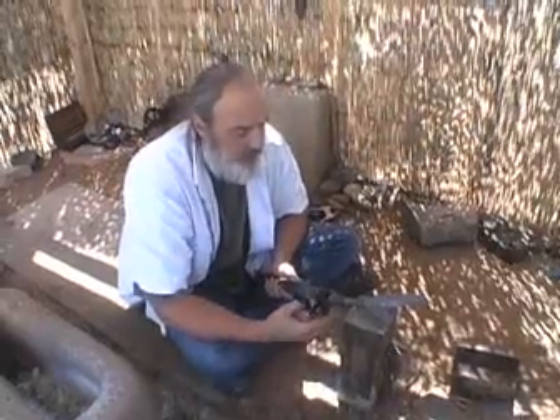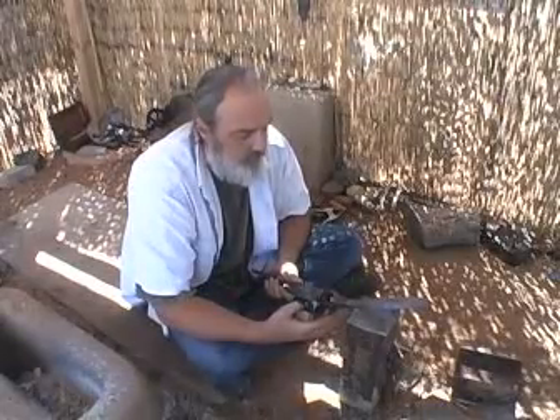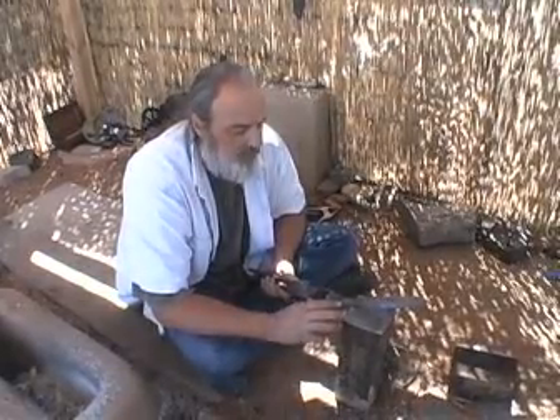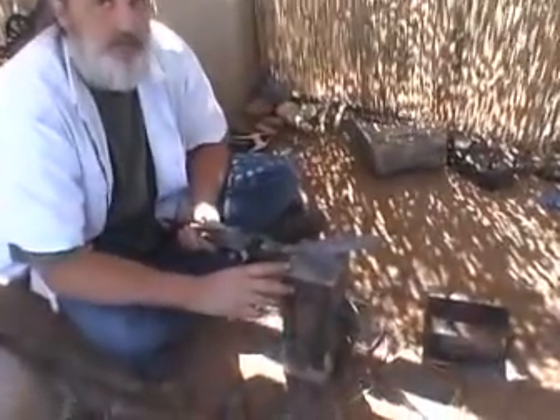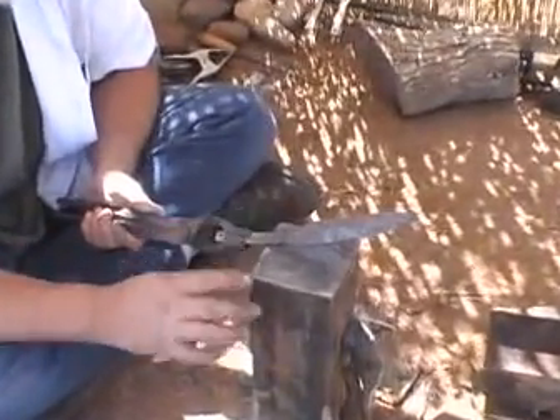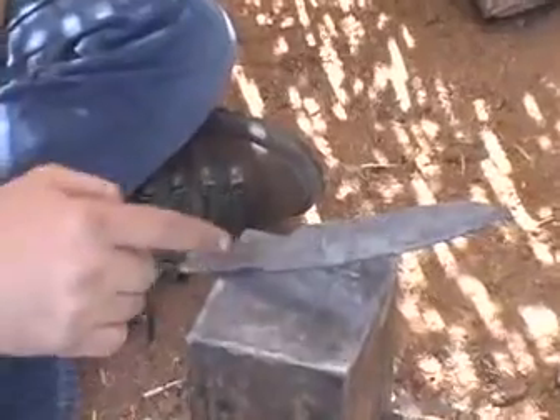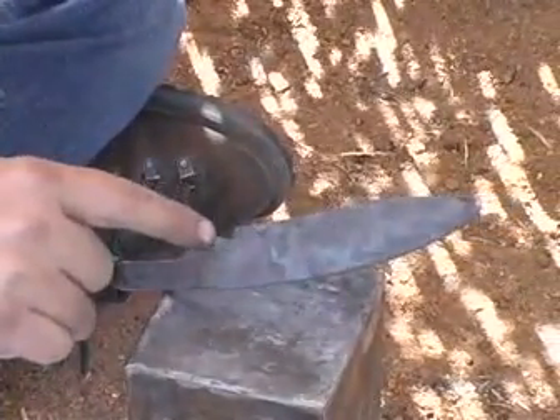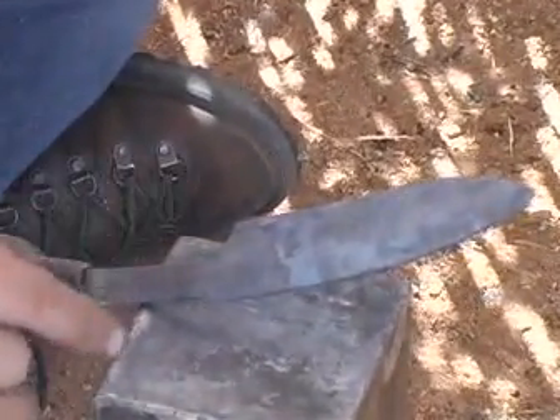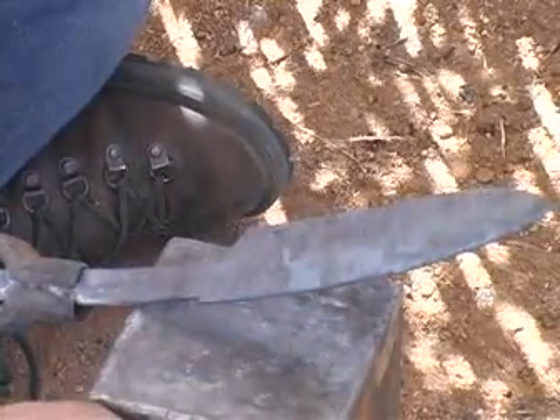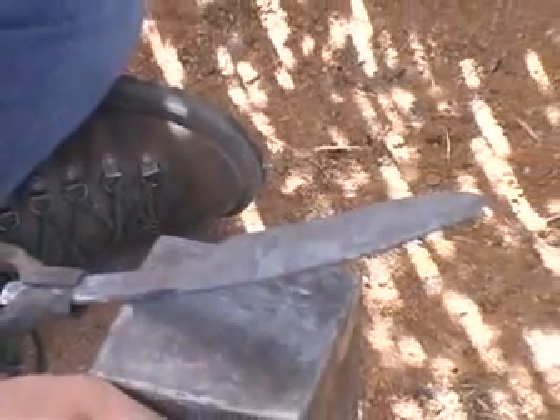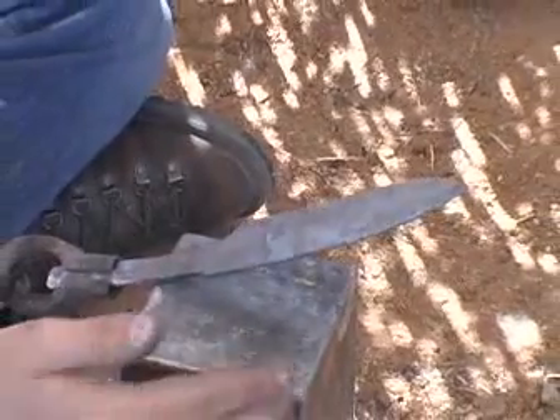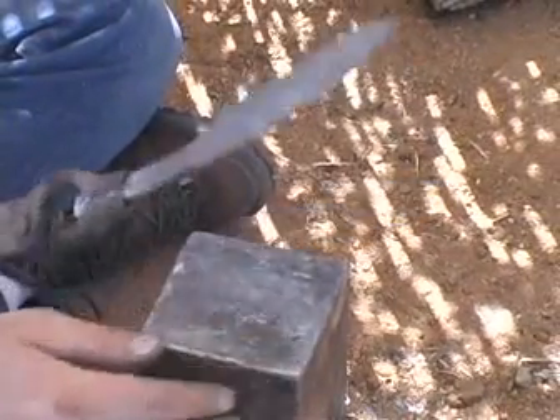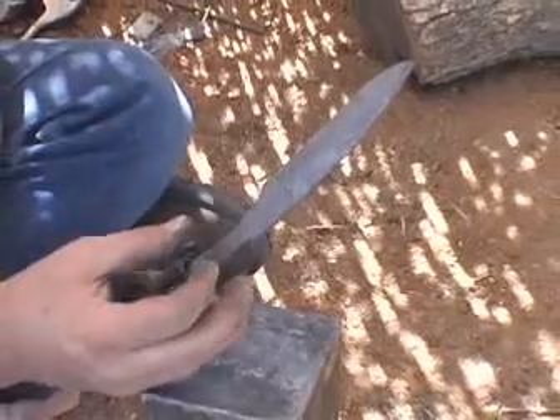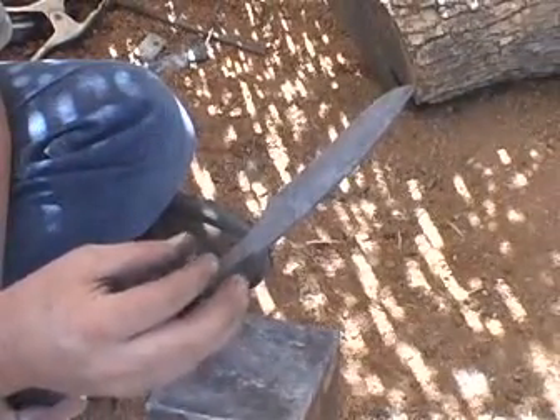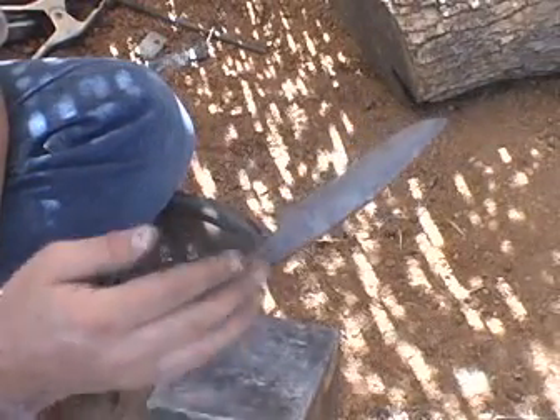The blade now is completely forged to its final shape. It's been slow annealed in the forge, in the ashes and the coals, and it's as soft as I can get it at this stage. So I've done little file work here and there, cleaned up my choil a little bit with a file. Less than 5% of the material has been removed so far due to stock removal by using files. I'm going to fit a handle up to it and get everything nice and square the way I like it while it's still soft, and then I'm going to heat treat it.